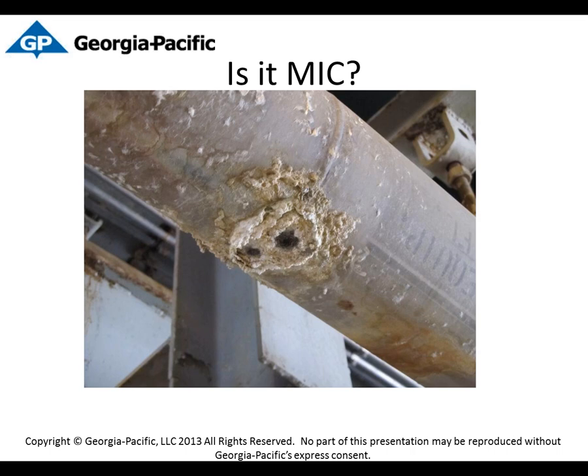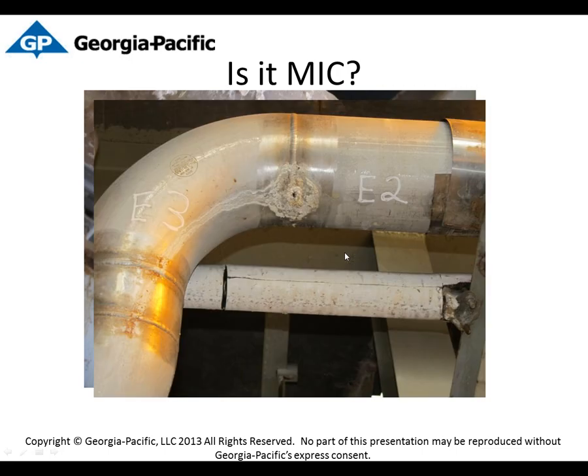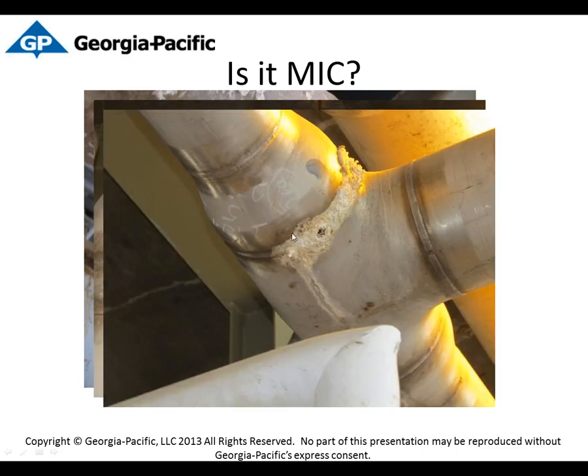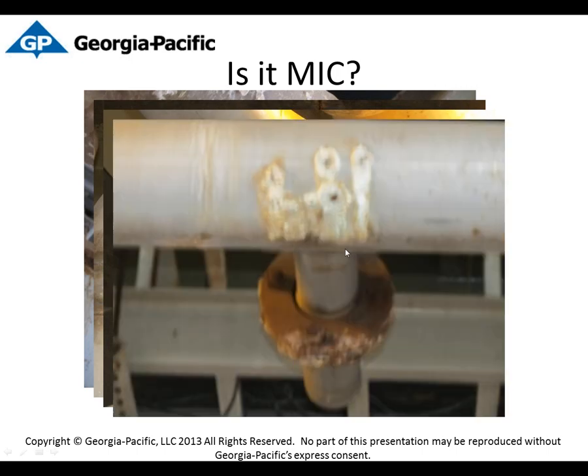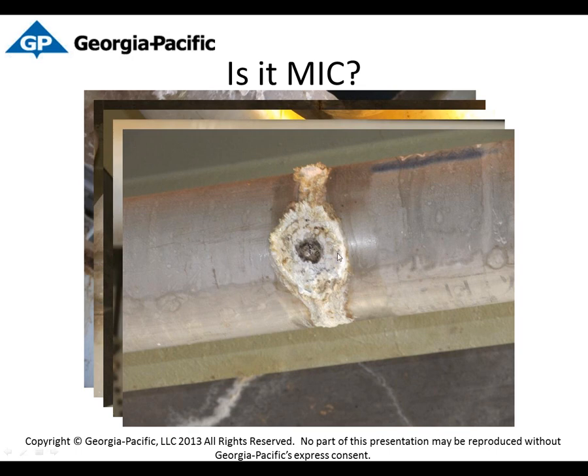and you'd see something on the bottom of a well that looked like this. You see what appears to be a leak in the bottom of the pipe. You start walking that line, and it looks like almost every welded connection on the bottom of the pipe shows some form or sign of corrosion. We think, well, surely when this pipeline was installed, we didn't have bad welds on every single joint of piping. So there must be something else going on there.